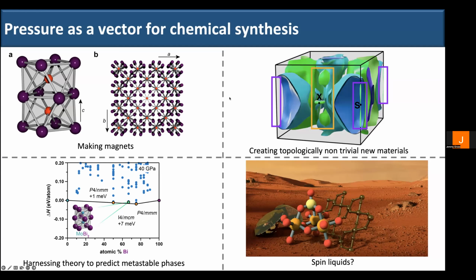Okay. And then the key part, as Eric mentioned, is the culettes, and that's the flat face of the diamond. And, you know, mass over area, right? So the smaller you make them, the higher pressures you can reach. So when you're talking about getting to pressures that are comparable to the core of the Earth, which is largely geophysics work and some work on high pressure hydrogen, for example, then you're talking about very small culet sizes, things that are outside of my area of expertise and highly controversial based on entertaining arguments of high pressure physicists. But at the pressures we're looking at, you know, 300 to 100 micron type systems.